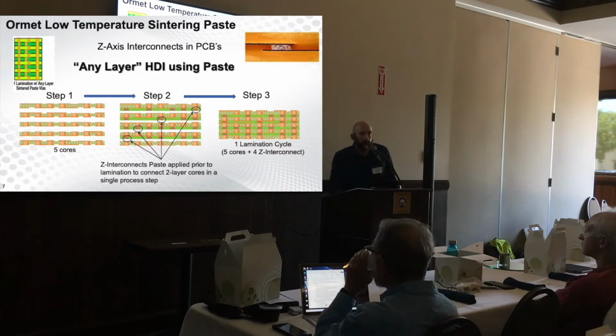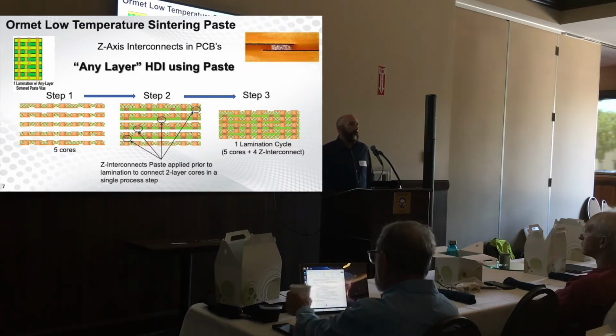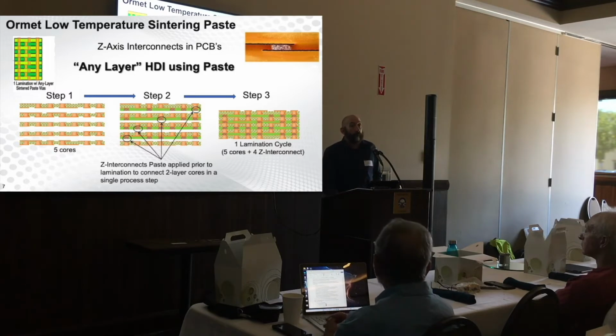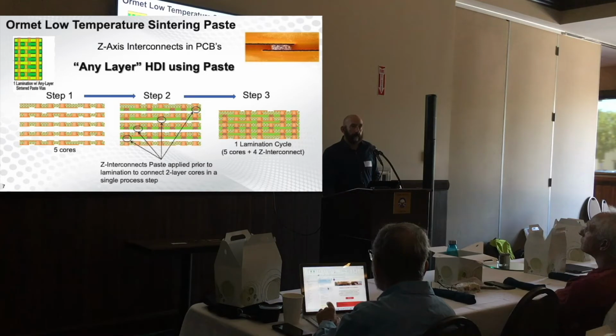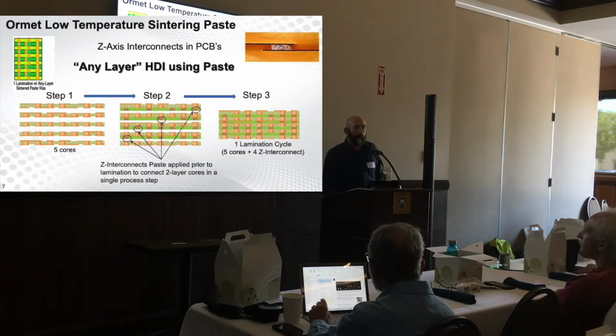Yes? What's the maximum dielectric thickness that it can handle? So we like an aspect ratio of 1 to 1 or less. So in other words, if you have a 5 mil diameter via, you don't want your dielectric any more than 5 mils. So the only negative, because I've used this on multiple products, is that to use any-layer via, you've got to have a lot of layers. If you're trying to do an 040 board, 062, it just takes a lot of layers. But why couldn't you split that into, well, two? That's what we've done before. Yeah, but if you do it like a pure any layer.